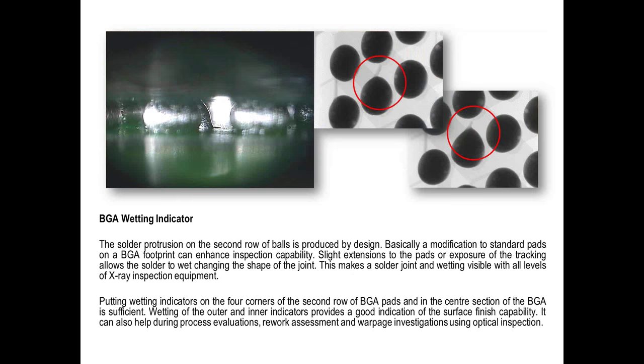Now, wetting on any surface, we like to be able to see it as readily as we possibly can. And this is just a very simple little trick which aids inspection, and possibly aids inspection if you haven't got the highest end piece of equipment for doing inspection. So optically, you can see how the solder has changed its shape on the left-hand side, and on the right-hand side, as I've highlighted, you can see the solder wetting to different degrees on what we refer to as a wetting indicator. So these are great to be able to monitor different materials, different processes, different board finishes, but also as an indication that your process is in control.